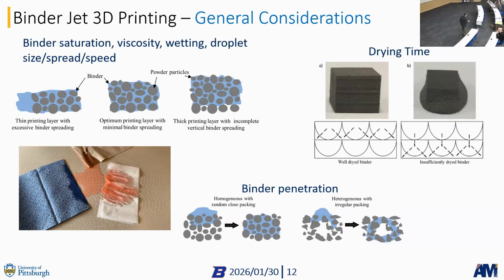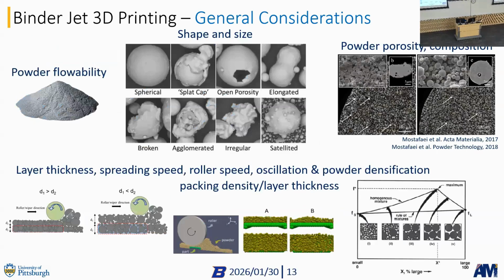Depending on what kind of powder you have, depending what kind of binder you have, the powder-binder interaction can be very different. Right? So you need to understand how this interaction actually takes place, how far your binder actually leaks in. Will you have nice shapes or will you have binder bleeding in your parts? You need to consider powder flowability, because if you have very sticky powder, like a very fine sugar, right, powdered sugar, then it sticks. If you have granular sugar, then it flows actually really well, right? So in binder jetting, it is always better to have flowing powder. You can also get around with non-flowing powder, but that's a different story.